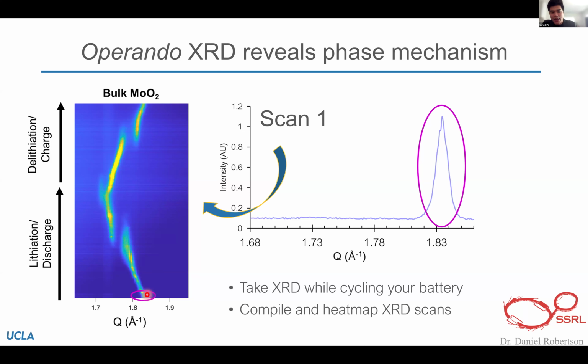We can watch as we discharge or charge our battery that our diffraction peaks shift. So we start at some 2 theta or Q value, which corresponds with a D spacing, right? So we move to a lower 2 theta, which, because we're in reciprocal space for X-ray diffraction, corresponds with an expansion of the unit cell. And this should make sense. We're putting lithium into our material, so we expand the structure.